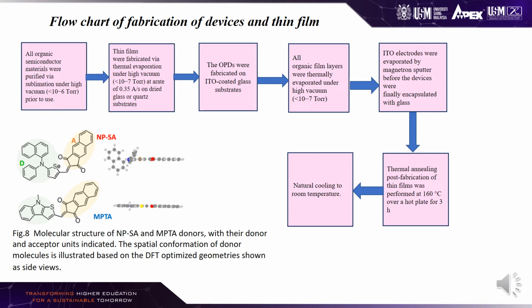Then the OPDs were fabricated on ITO coated glass substrate. The next step is all organic film layers were thermally evaporated under high vacuum, which is lower than 10 to the power of -7 torr. Next, electrodes were evaporated by magnetron sputter before the devices were finally encapsulated with glass. Next, thermal annealing post-fabrication of thin films was performed at 160 degrees Celsius on a hot plate for 3 hours. Finally, they are left to cool naturally to room temperature.